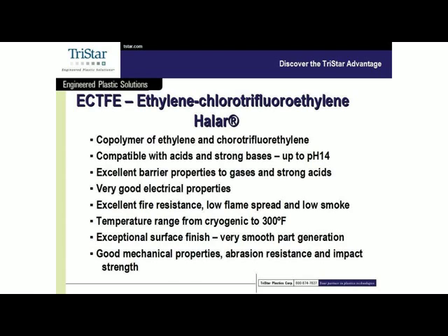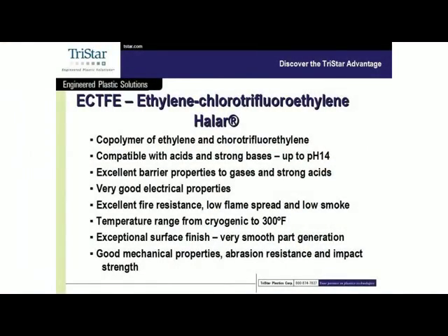Electrical properties are very good. Sometimes when you introduce a chlorine, which we do have in this particular version of fluoropolymer, the chlorines tend to degrade the electrical properties slightly, so that's something we need to take a look at if you're concerned about certain dielectric factors. Excellent fire resistance, got low flame spread and low smoke generation. The temperature range on ECTFE is cryogenic up to 300 degrees Fahrenheit. It is one of the other favored materials for cryogenic applications.